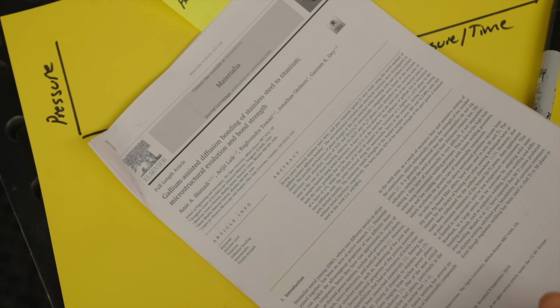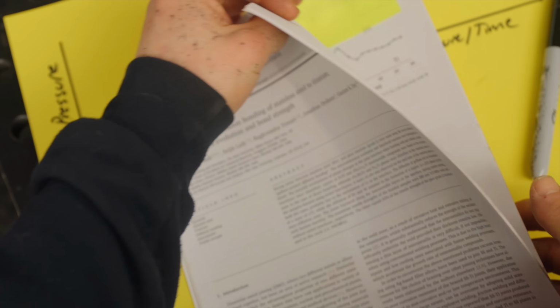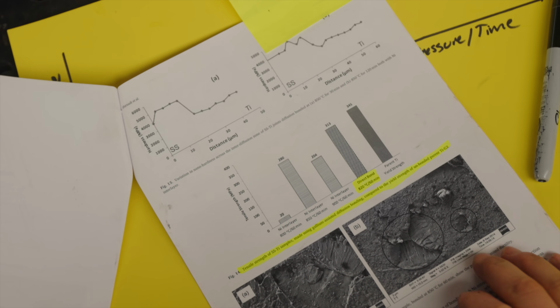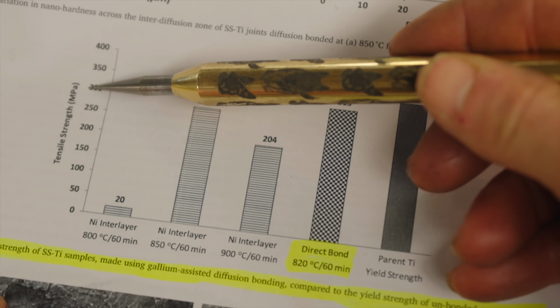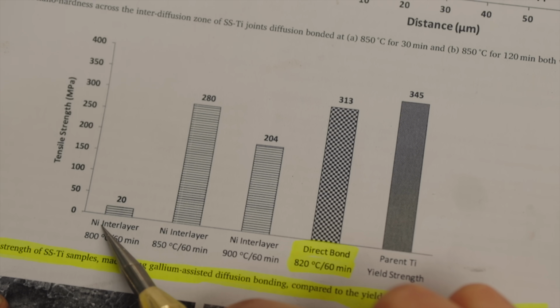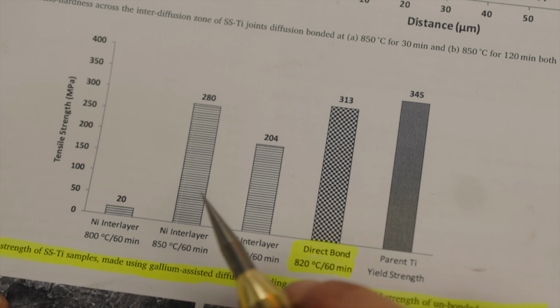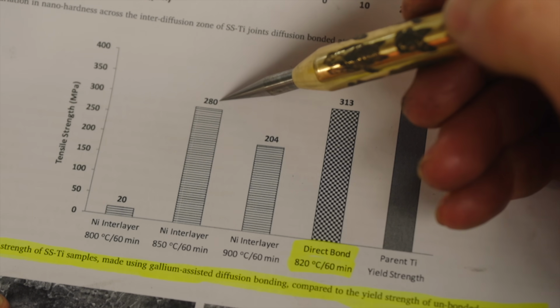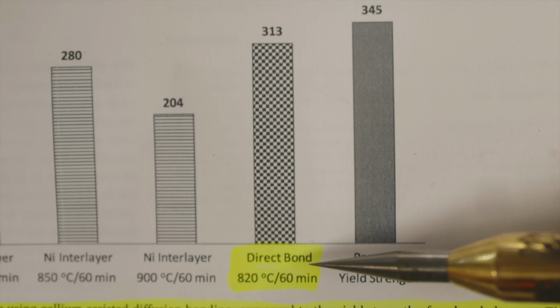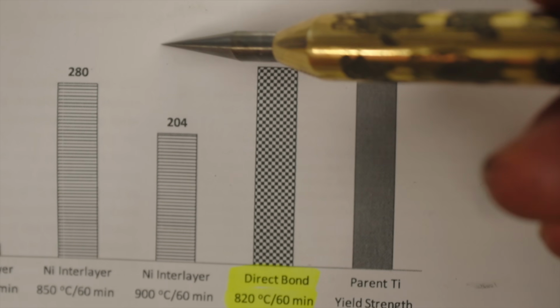He opened up this paper, which you can find online, and this is some of his research on bonding stainless steel to titanium. And if you look at his tensile strength results, you will see that with a nickel interlayer, the optimum bonding temperature was 850 degrees Celsius with a 60-minute bond time, but a direct bond with no interlayer was even stronger. And I'm like, what on earth is going on?